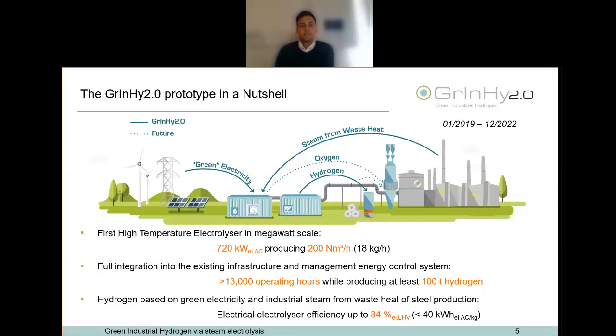The system is fully integrated into the existing infrastructure. So it's connected to the pipelines of hydrogen, nitrogen, and also steam. And the system is controlled, same as any other production process that we have here on site, by our centralized energy control system. By doing so, we want to reach more than 13,000 operating hours during the project duration. And with that, we'd like to produce at least 100 tons of green hydrogen.